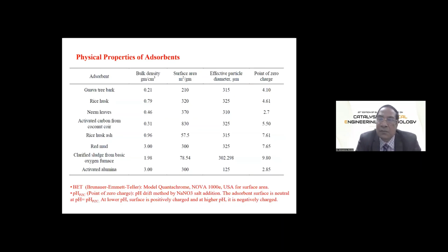Then we have done some other physical properties also, like bulk density, effective particle diameter, surface area, and point of zero charge. Surface area we have measured through BET method, and you can see here good surface area in a unit of meter square per gram is there for all the adsorbents. And point of zero charge we have done through the pH drift method by adding sodium nitrate solution. Point of zero charge means at this particular pH, the adsorbent surface is neutral.